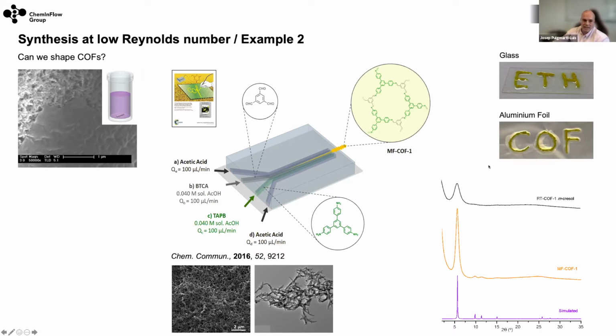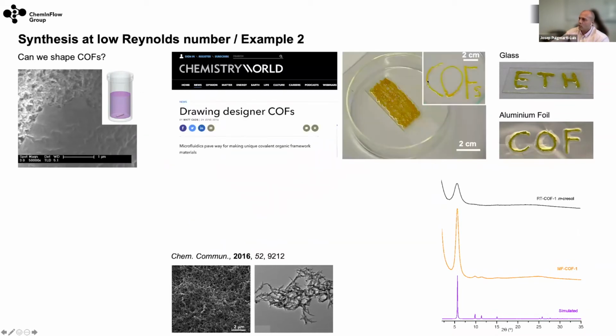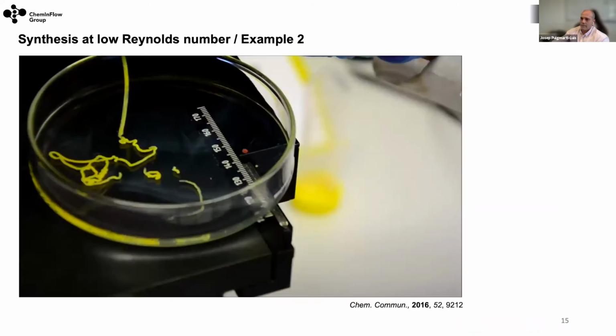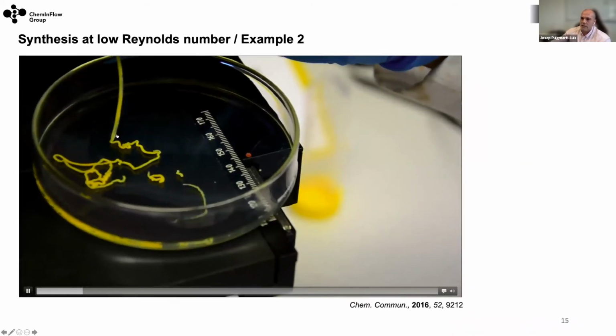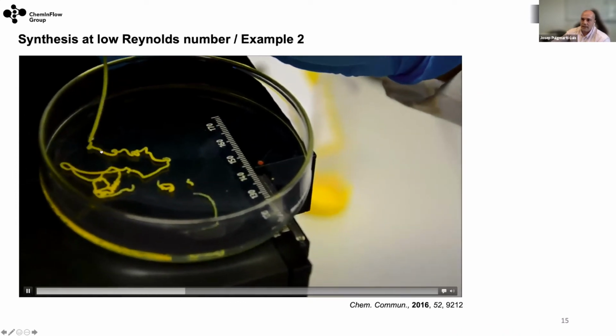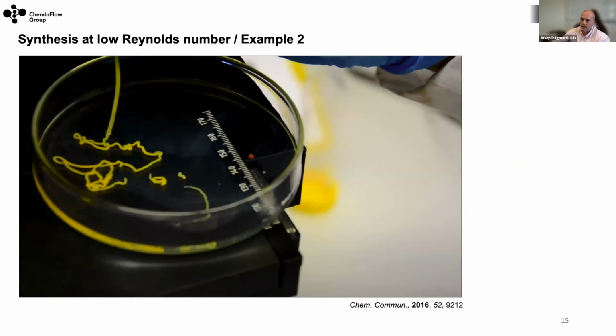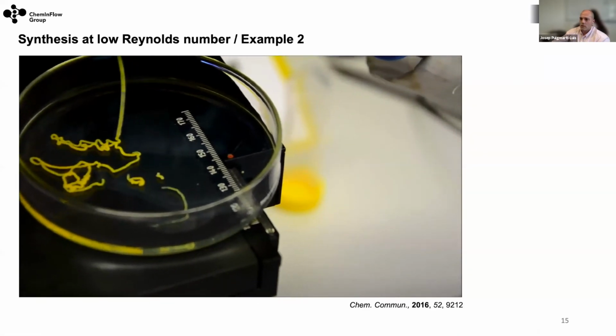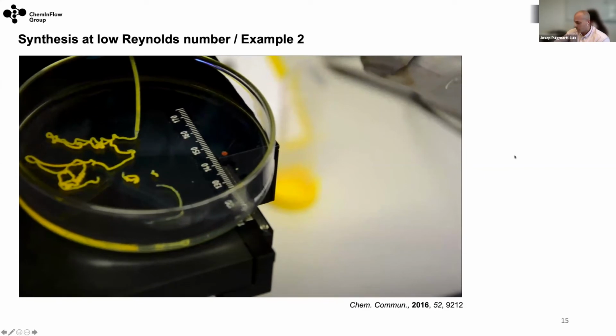What we can do is we can process the COF now. COFs are very difficult to process because they are very difficult to dissolve, and therefore it's very difficult to print them. Here what we could do, and this was highlighted in Chemistry World, was to 3D print the COF in arrays and also write different words on different surfaces. So let me show you the video. This is the outlet of the microfluidic device, and what you observe here is the COF fiber that we are generating via this microfluidic approach. We were very happy with these results.